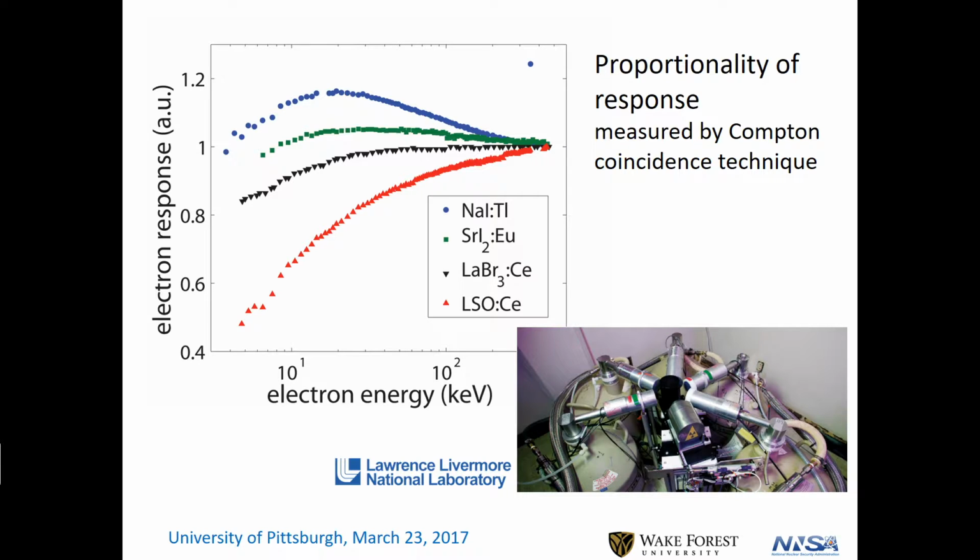And so here it is. We get the way to quantify that nicely so that we can try to work with something that's quantifiable. It's called proportionality. So finally, that word I used up front, non-proportionality, that's the fact that these are all curving. So the ideal, the perfect detector for resolution would be just a horizontal line, because they're normalized out here at 662 keV, but a horizontal line would say you get that many electron hole pairs for that many eV, regardless of the number of eV you have.